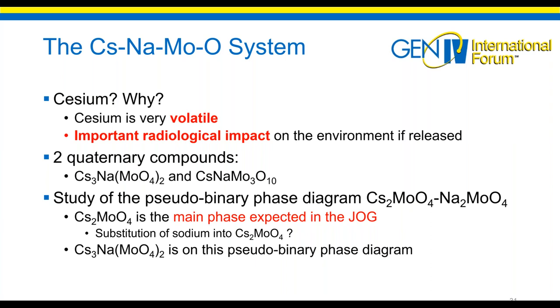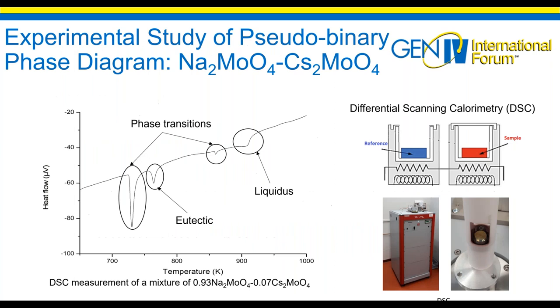So you have two quaternary compounds in this system. We did exactly the same structural measurements, but I will not detail them here. I will focus more on the study of the pseudobinary phase diagram Cs2MoO4, Na2MoO4. In fact, Cs2MoO4 is the main phase expected in the joint oxide gain. And therefore, in case of a severe accident, you could have a substitution of sodium into this Cs2MoO4, or a reaction between the sodium and these compounds. Moreover, on the pseudobinary phase diagram, Cs2MoO4 and Na2MoO4, one of the quaternary compounds exists on this pseudobinary. So you have two reasons to study this, and it will be used to build the CALPHAD model also.